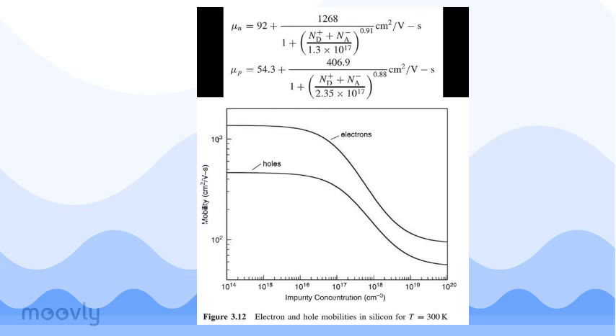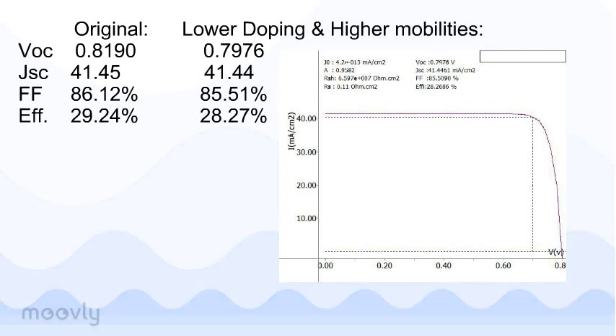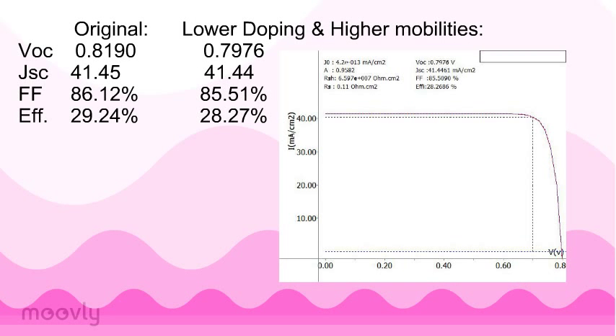When we adjust this model to account for the change in emitter doping density, we can still see that the results are pretty much the same. So now, let's account for the change in hole and electron mobilities if we decrease the doping density to the order of 10 to the 16th. Our electron mobility is now an order of magnitude greater. As you can see, this reduced our open circuit voltage. Therefore, when you are changing the doping density, you need to make sure that you account for the change in hole and electron mobilities.